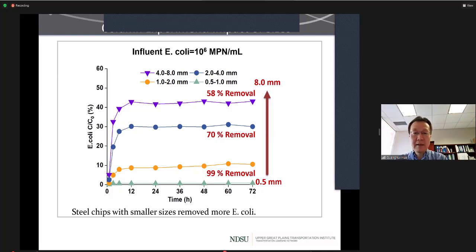And we learned that as the size becomes bigger, the removal efficiency gradually declines. For example, for the fine size particles, 0.5 to 1 millimeter, we were able to achieve constantly about 99% removal. And as the size increases, we found that the removal efficiency gradually declined to about 58% for the highest size material, which is 4 to 8 millimeters.